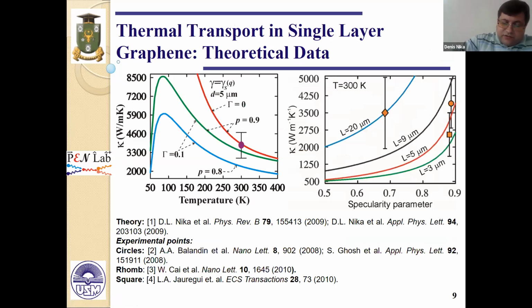Calculated dependencies of thermal conductivity on temperature are shown in the slide in the left panel for different concentrations of point defects and different parameters of edge roughness scattering. In the right panel, you can see the dependence of thermal conductivity on the specularity parameter, shown for flakes with different lateral sizes.